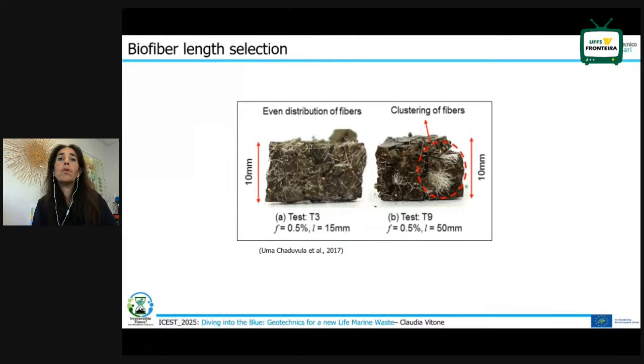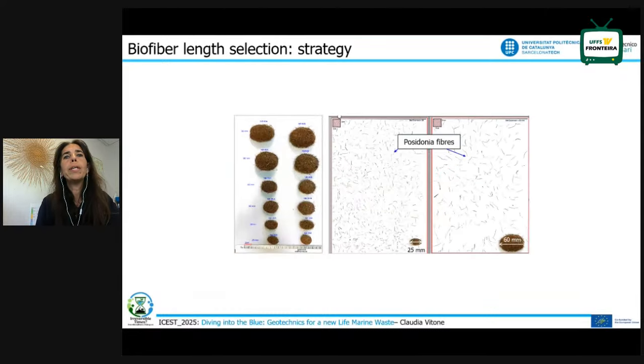So another point was that of trying to select the length of these fibers. Since these are not artificial fibers, we could not pre-select the fibers, it is very important to have the possibility to select some length, because we have to avoid the clustering of the fibers. So what we did was to open these balls. So you can see here, this is one ball of 25 millimeters diameter, more or less opened. And this is another ball of 60 millimeter diameter open.